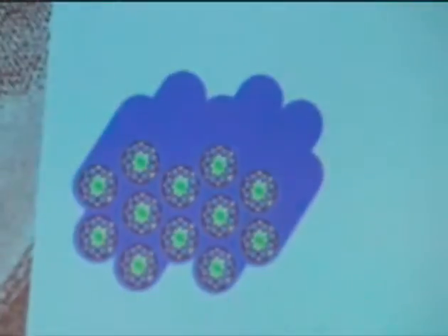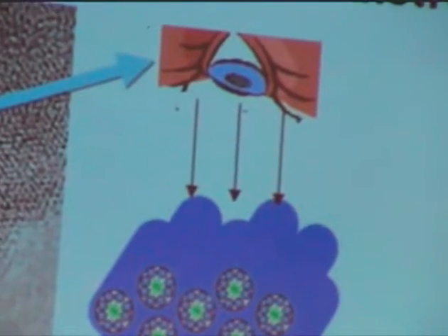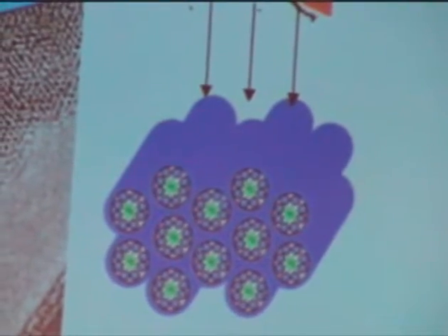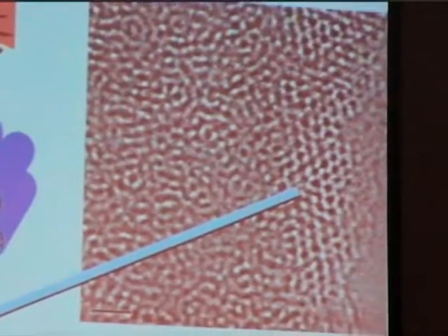But our interpretation of those stripes is that we have the 2D hexagonal structure. So we have cylindrical pores, but we're looking along the edge of the pores. That would look like stripes because you're just seeing the edges of an array of cylinders. If we zoom in on this region of the image, you can see there are little circles, which indicates that we're looking down the channels of this 2D hexagonal structure. So we're actually looking into the channels.